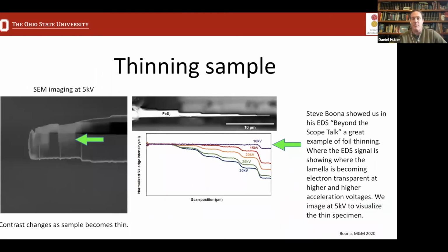Once that sample has been put on the Omni probe grid, we can go back and do some thinning. I think Steve in his EDS talk did a really good job showing an example of a TEM foil where he thinned it in a stepwise fashion, and then scanned the sample with the electron beam at various different voltages and looked at the X-ray emission, one of the signals that comes out of the sample. As you can see, this is iron disulfide, and when the sample is thicker you get some transmission through the sample at 30 kV. As you go down in accelerating voltage from 30 to 20, 15 and 10, the transmission keeps happening at thinner and thinner parts of the specimen. So this highlights the trick that we use when thinning the specimen with the ion beam to check its thickness.